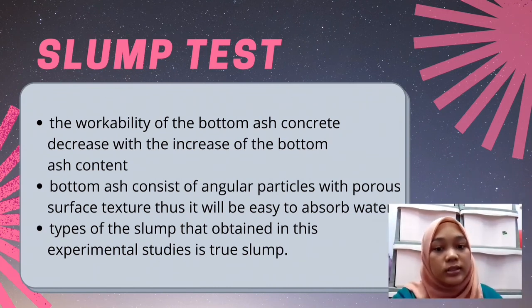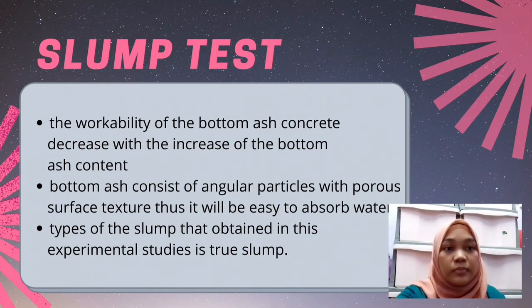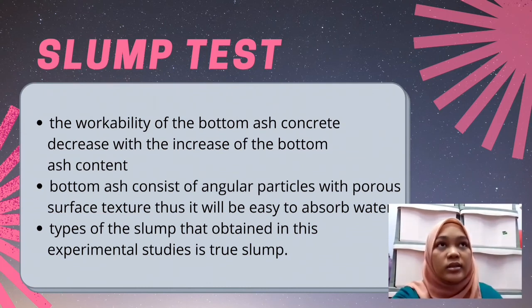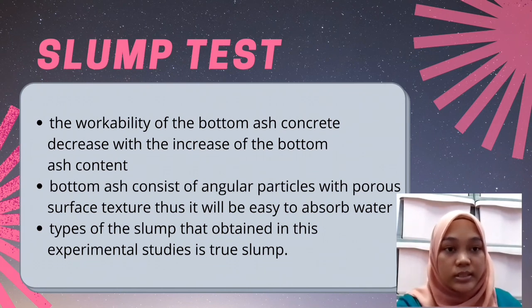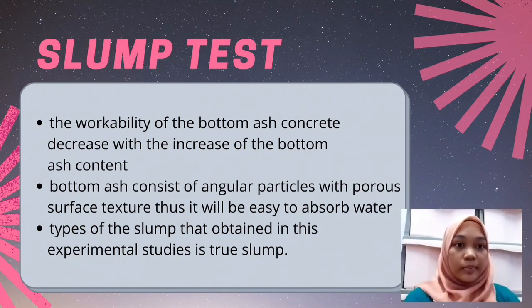Based on the studies conducted by the researcher, the slump test determined the workability of the concrete. The workability varies when different percentages of bottom ash are added into the cement. The workability of the bottom ash concrete decreased with the increase of the ash content. Bottom ash was found to consist of an angular and very porous surface texture. Thus, it will be easy to absorb water. Slump can be classified into three types, which are true slump, shear slump, and collapse slump. In these studies, the type of slump is a true slump.